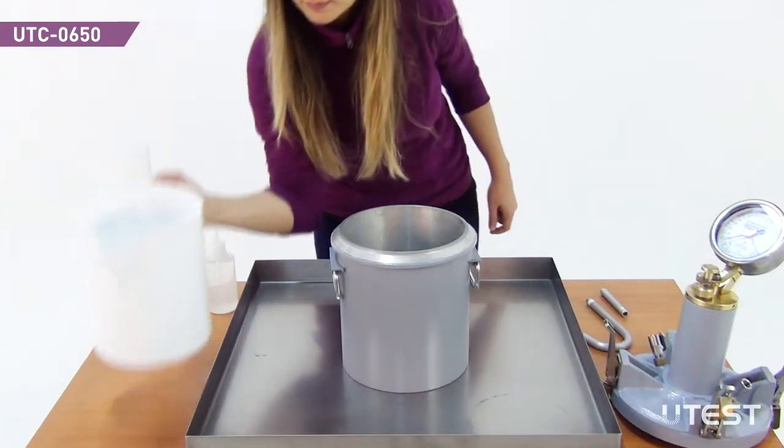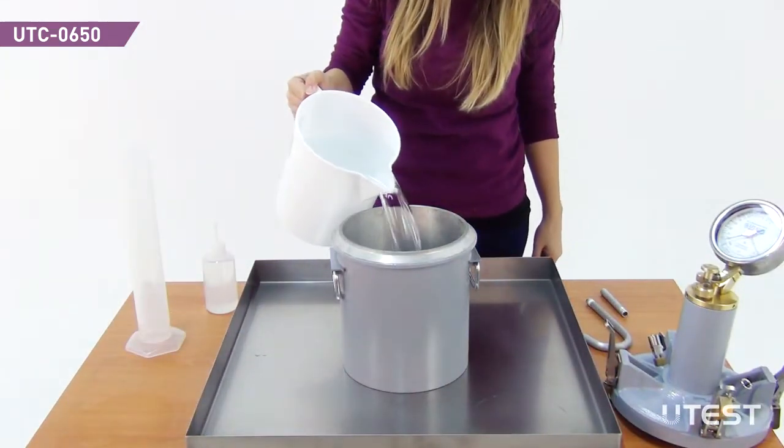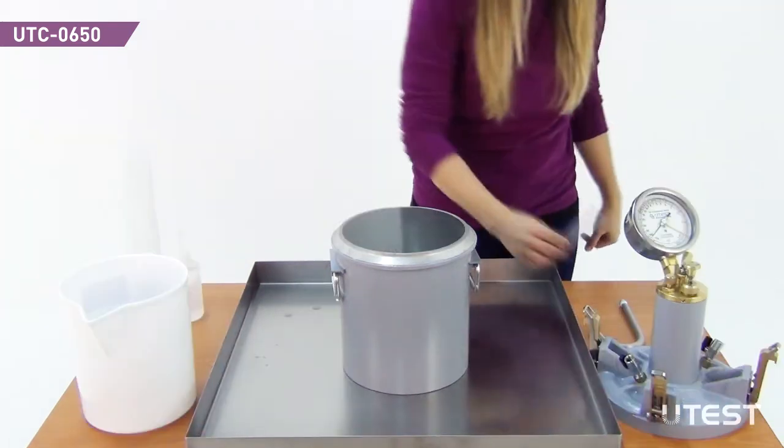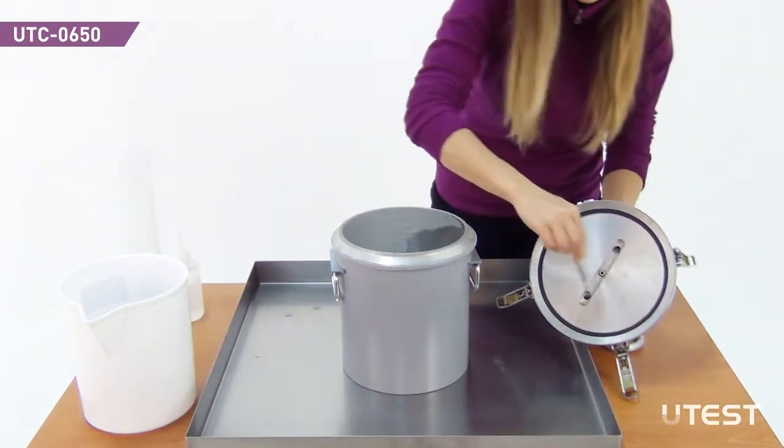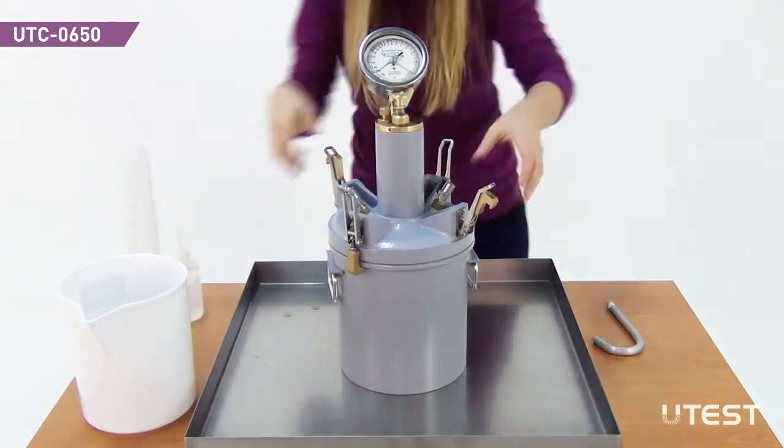For calibration, fill the measuring bowl with water. Screw the short tube into the threaded petcock hole on the underside of the cover lid. Then close the cover lid.